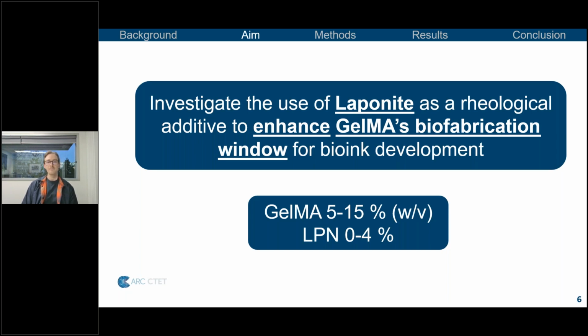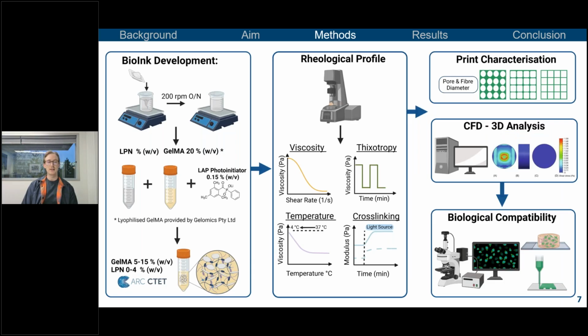The general methodology focused on bioink development, achieving these different concentrations, and then undergoing a rheological profile looking at 4 main characteristic tests: viscosity for shear thinning capability, thixotropy to look at shape fidelity and viscoelasticity, a temperature sweep to look at what printable temperature we'd like to achieve, and the cross-linking and mechanical characteristics. This was followed by printing characterization of fiber and pore diameter for the optimal printability window, then some CFD simulations in 3D to get an idea of the shear stresses that were occurring, followed by biological compatibility.